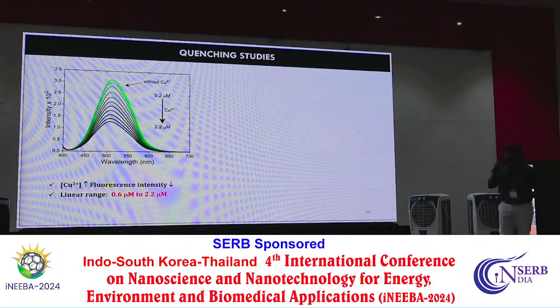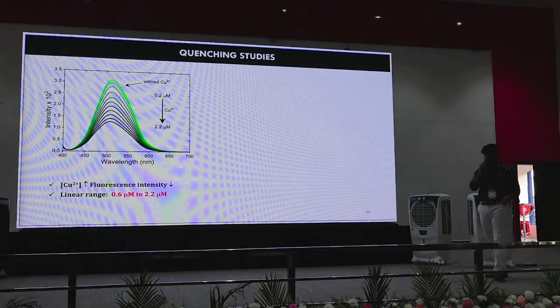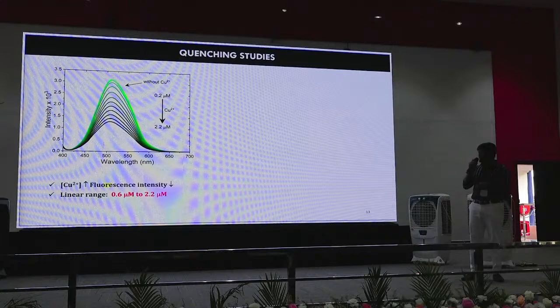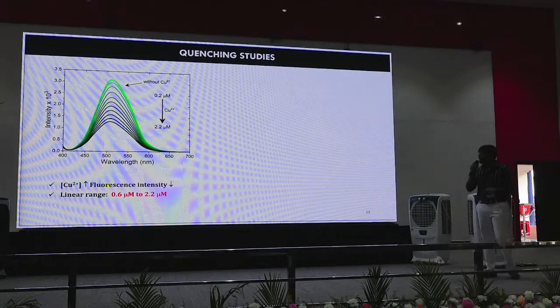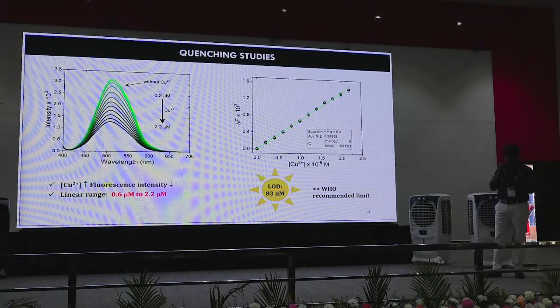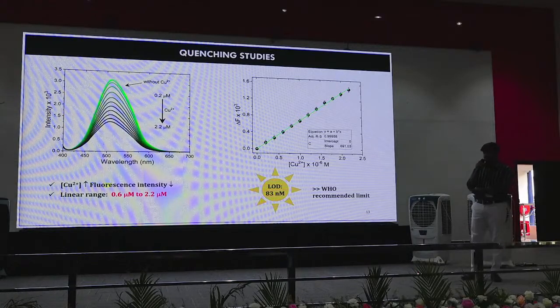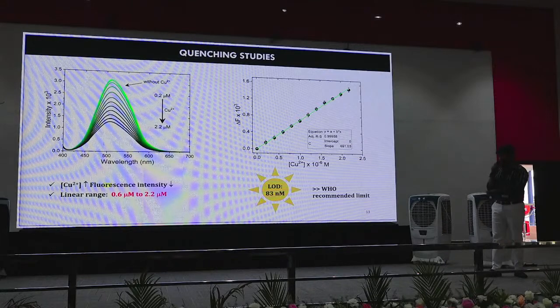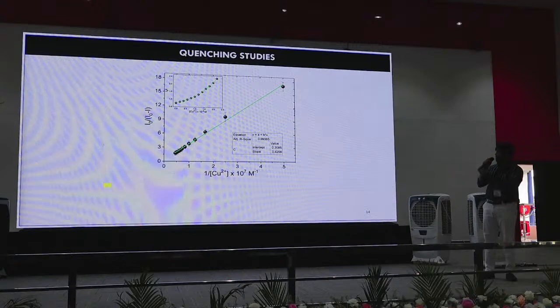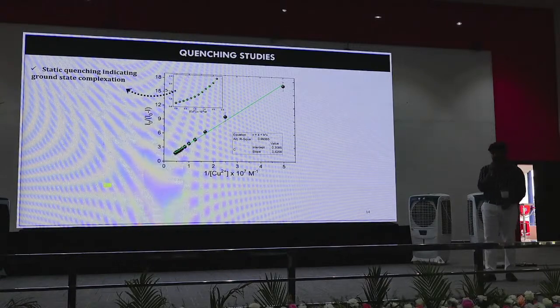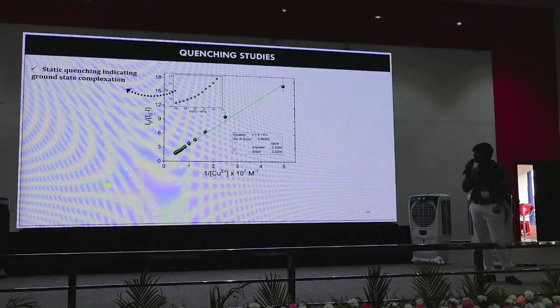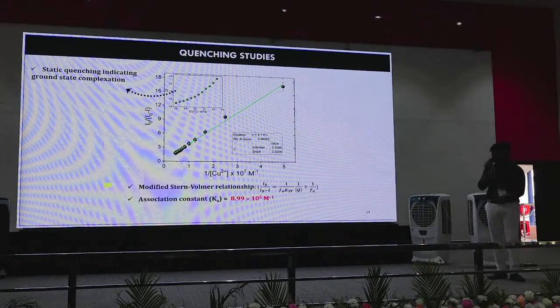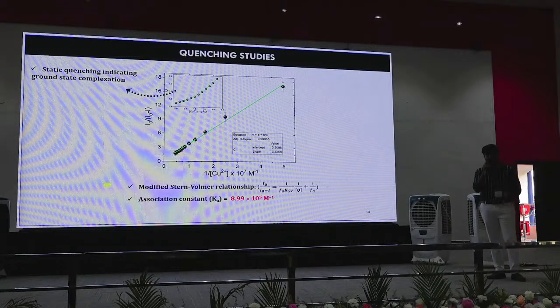And we did quenching studies. As we increased the concentration of copper, the fluorescence intensity decreased with a linear range. And we found the LOD to be 83 nanomolar, which is threefold lower than the WHO recommended limit. In the quenching studies, we also did a Stern-Volmer plot, which proves that complexation has occurred in the ground state, since there is an upward curvature. And we also found the association constant to be 8.99. This is the driving force for the better LOD.